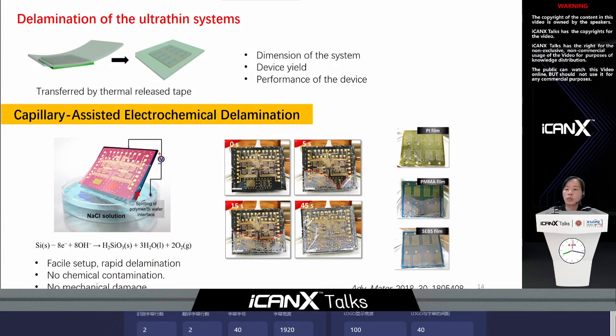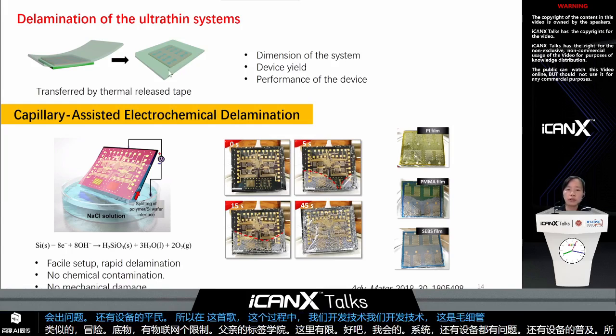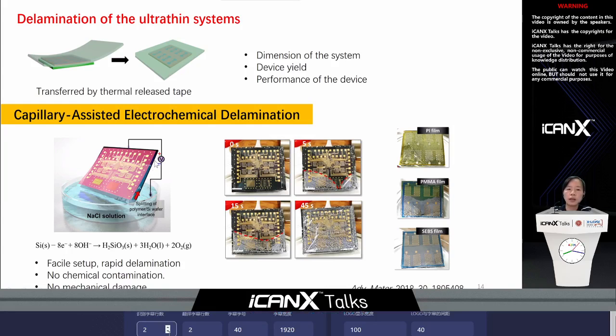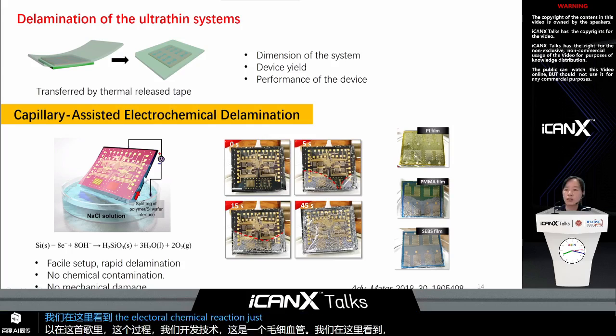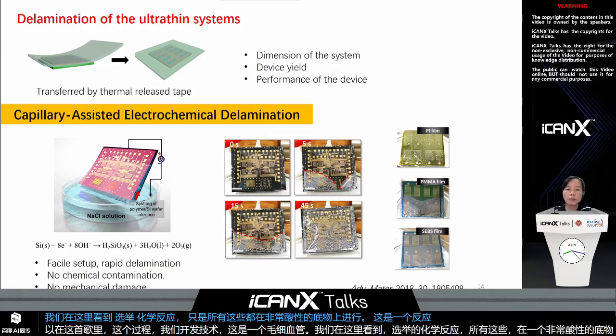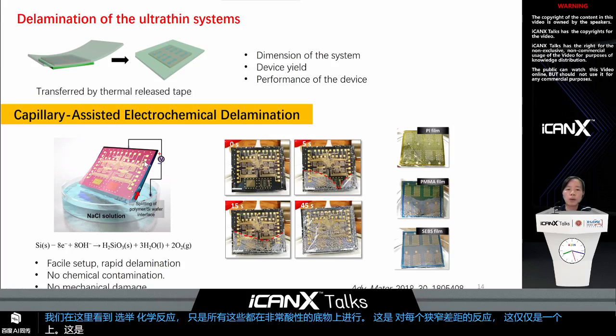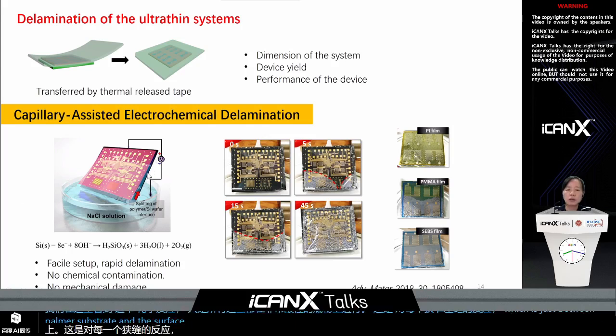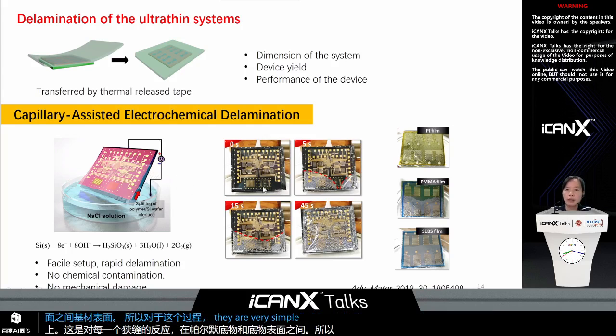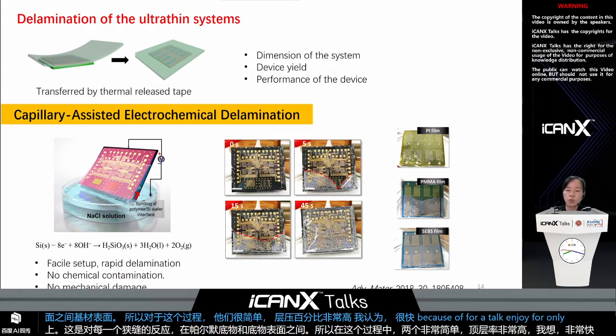capillary-assisted electrochemical delamination. In this process, the electrochemical reaction happens just on the silicon surface. Here is the silicon substrate, and the reaction is happening in a very narrow gap, just between your polymer substrate and the surface of the silicon substrate. For this process, the setup is very simple, and the delamination is very quick, because for a 2-inch wafer, it only takes 40 to 50 seconds.